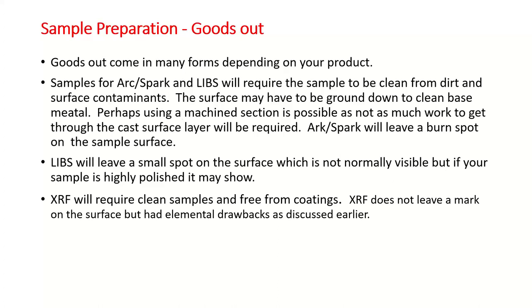LIBS will leave a very small spot on the surface, which is not normally visible, but if you've got a highly polished sample, it may show. So if you've got something that's a prize sample that you're sending out, maybe it's a bar pump or something like that for beer, maybe it's a body implant, and you're looking at the actual ball of a hip or something like that, you wouldn't want to be testing on there with something that's going to leave a small mark, because it would be noticeable. It could cause problems in the future. XRF, you need a clean sample, again, free from coatings, but it doesn't leave a mark. So it's very good for samples where you can do quick testing.